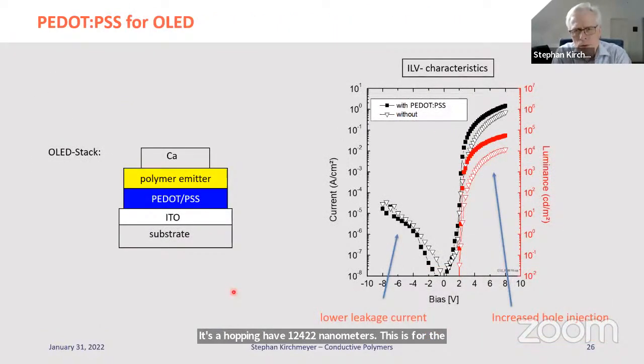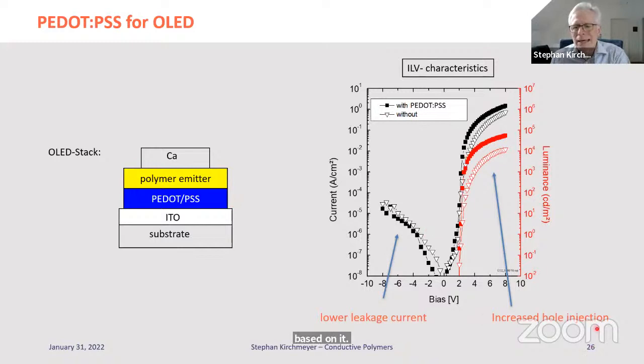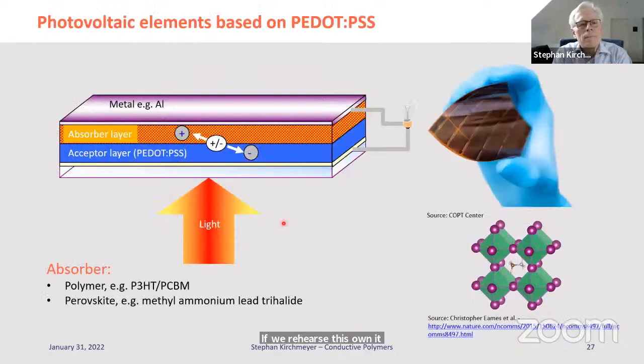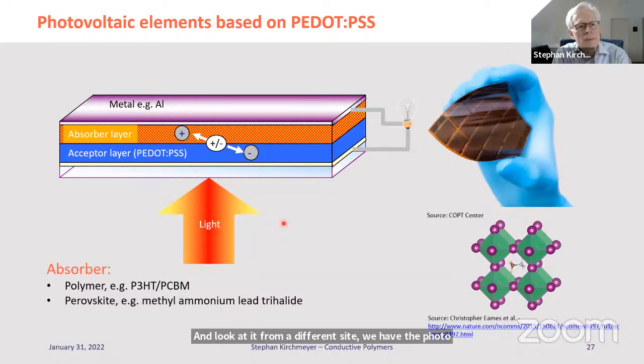Last but not least, I will also mention that PEDOT was proposed to be used for OLED, solvent-based OLEDs. It works. It has two effects. First of all, it increases the hole injection, but it also smoothens the layer and has a lower leakage current. If we reverse this OLED and look at it from a different side, we have a photovoltaic element, a solar cell, and then PEDOT is used basically in a very similar setup as an acceptor layer and together with an absorber, which makes the charge separation.